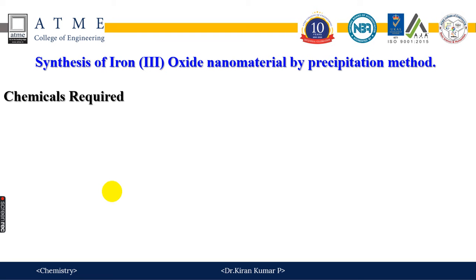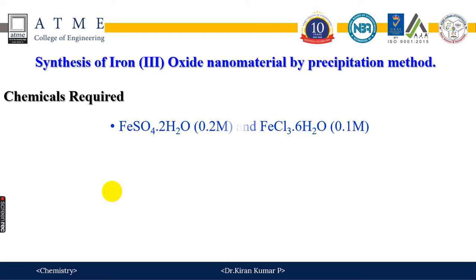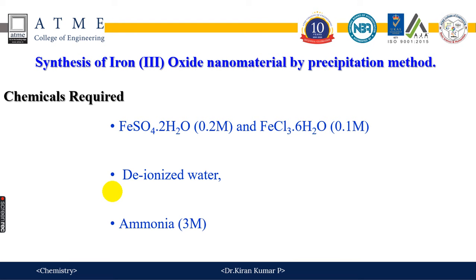The chemicals required for the synthesis are FeSO₄ of 0.2 molar, FeCl₃ of 0.1 molar, deionized water, and a base — ammonia of 3 molar.